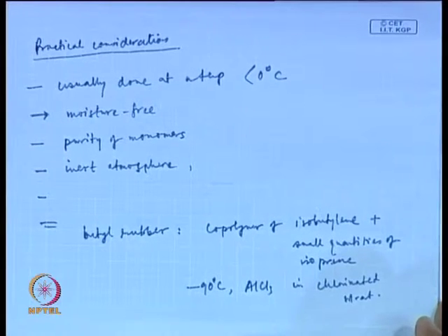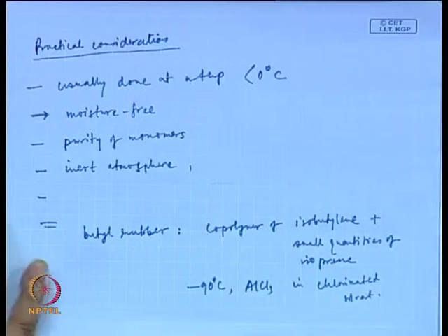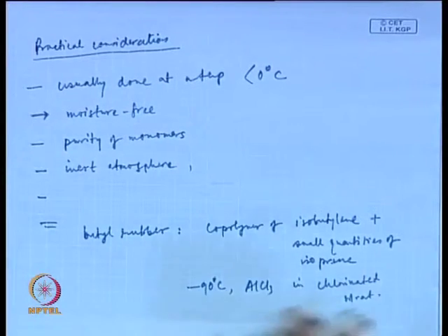remains flexible at low temperature, like minus 50 degrees. So, they are used in the inner tubes of tires, engine or auto body mounts, electrical cable insulators, protective gloves, etc., and some pharmaceutical stoppers. So, this is the only polymer or copolymer which utilizes this cationic chain polymerization commercially.